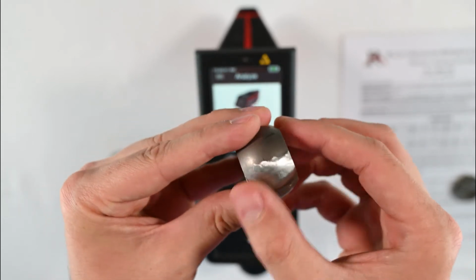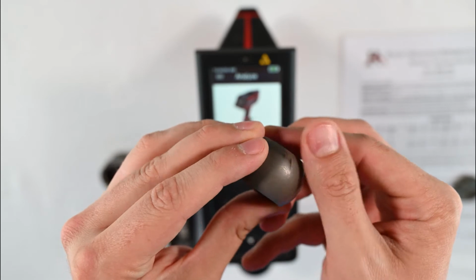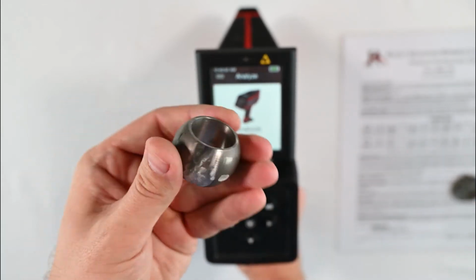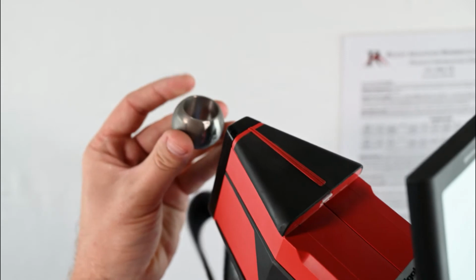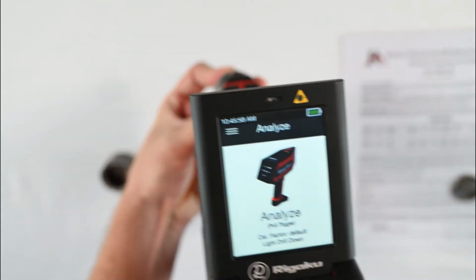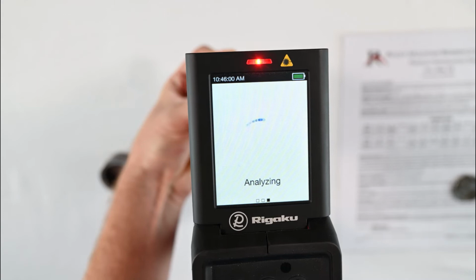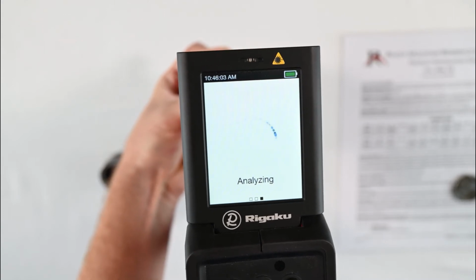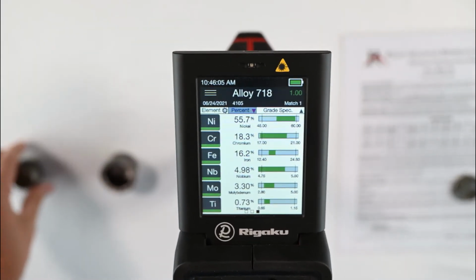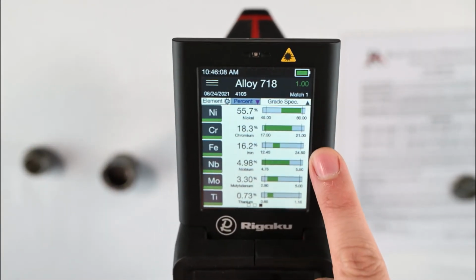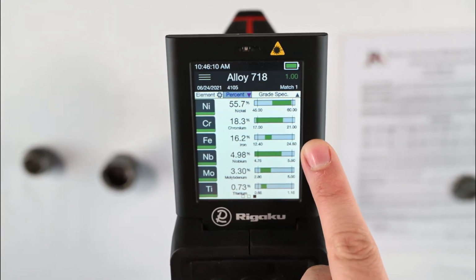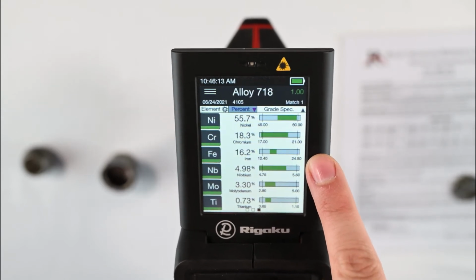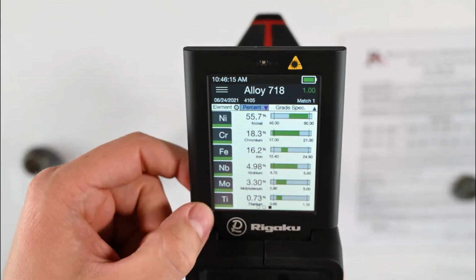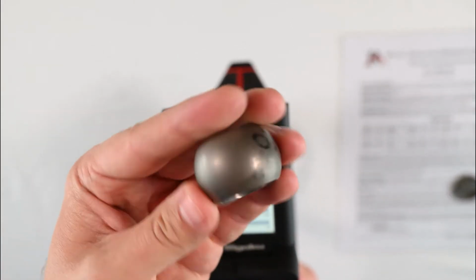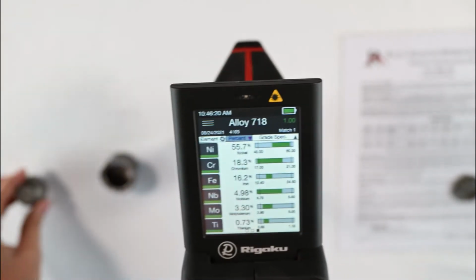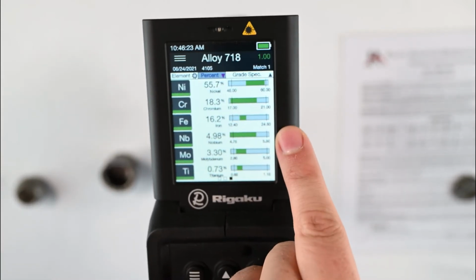But you'll see the color difference: this white pure metal and this oxidation. Typically cleaning the samples when they come out of service is a really good idea. If you're going to test this material, you just approach it with the analyzer like this, and I'm actually hitting the spot that we prepared, that we ground a little bit. There you go. And then boom. Okay, so here we have 100% match to 718. Now that's sorting a scrap part that we didn't know the alloy. Somebody wrote INCO on it, but at the same time we're able to see what that chemistry is. Now I don't know the actual chemistry of this part, but we do know with 100% confidence that it is 718.